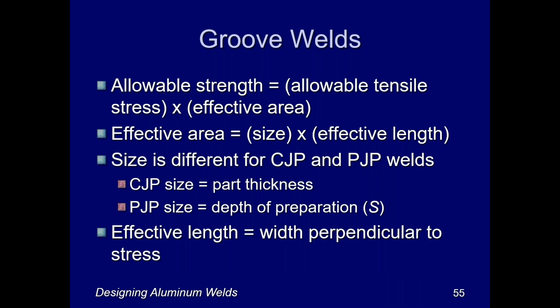Now, in order to determine the allowable strength of a groove weld, we take the allowable tensile stress times the effective area of the weld. The effective area is going to be the size of the weld times the effective length of the weld. Now, the size is different depending upon whether we have complete joint penetration or partial joint penetration.